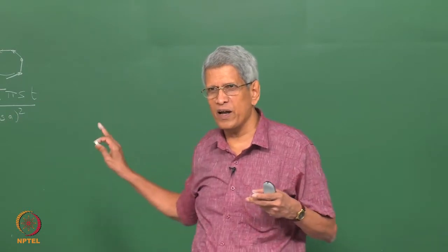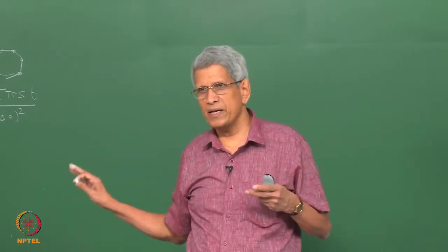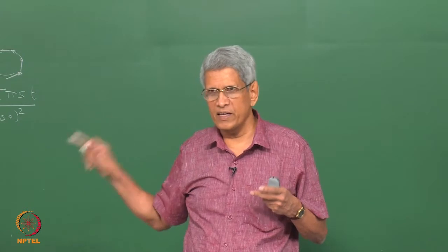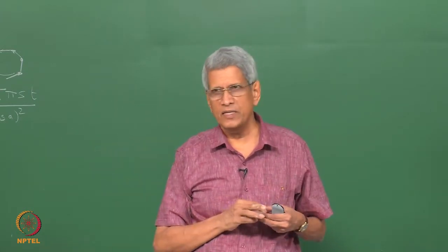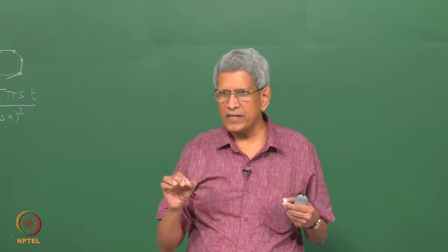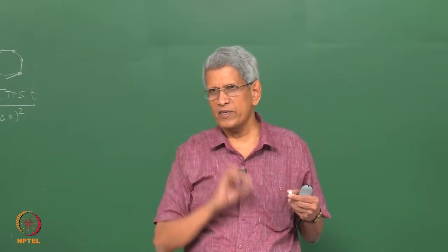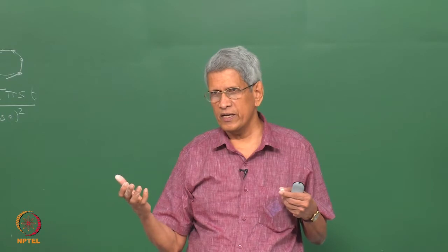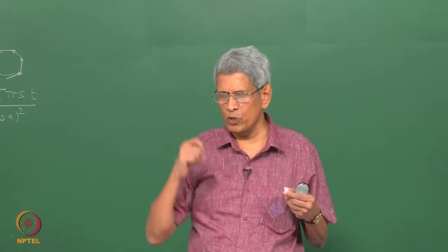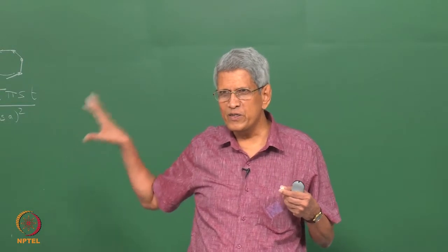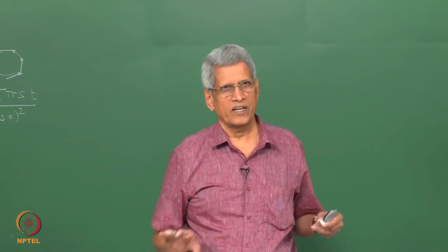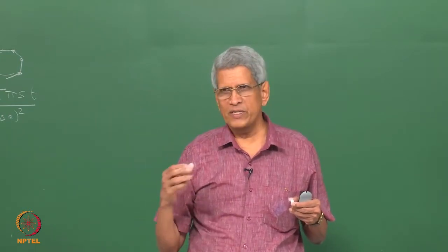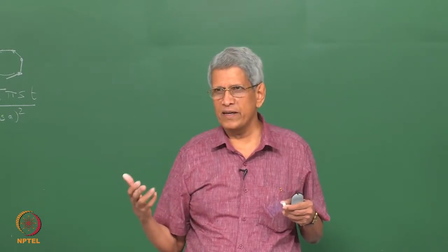This theory can be applied only when S is small, or when S is large, meaning the deviation from the Bragg condition is large, and the intensity of the diffracted ray is much smaller compared to that of the transmitted. When the intensity of the transmitted and the diffracted beam become very close to each other, that takes place under the condition when S becomes equal to 0. Under that condition, this theory is not able to explain the observed contrast. So, we have to develop a theory which is called the dynamical theory of contrast.